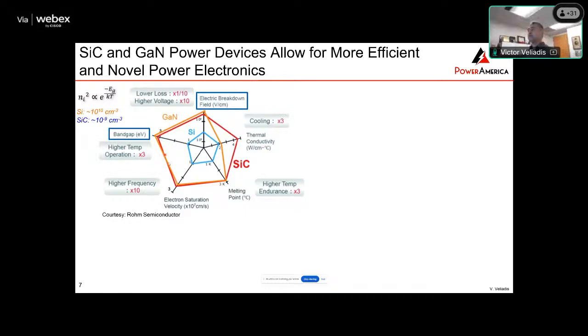So if you look at this spider graph here, you can see silicon carbide material properties are denoted in red, gallium nitride is in orange, and silicon properties are in blue. You can see that the electrical breakdown field, the critical field in silicon carbide and GaN, is about 10 times higher than that of silicon. The second thing I would like you to note is that the wide band gap of silicon carbide and GaN is 3 times higher than that of silicon.